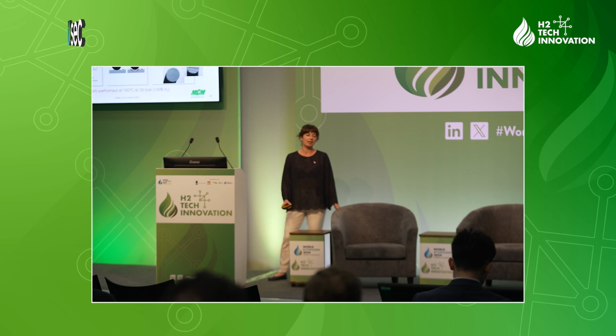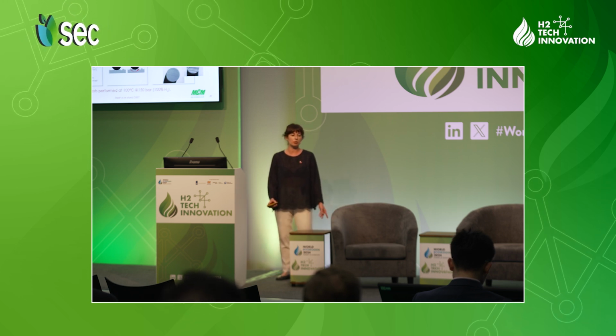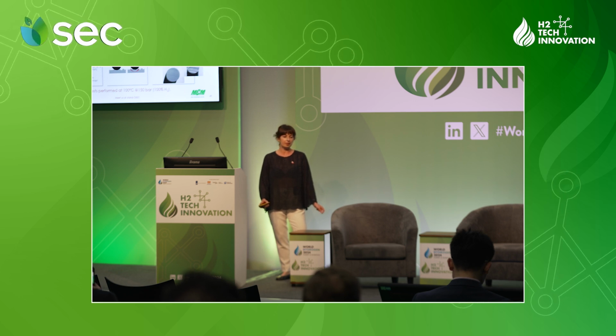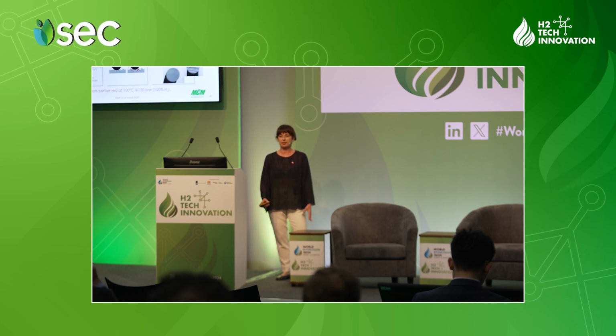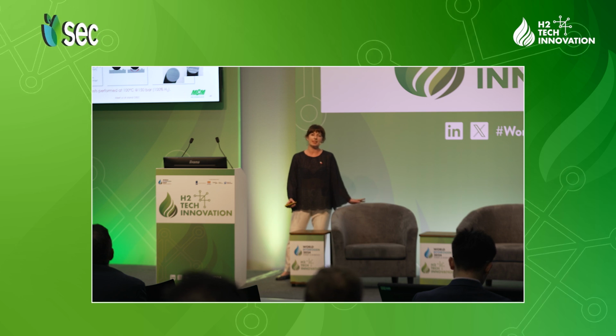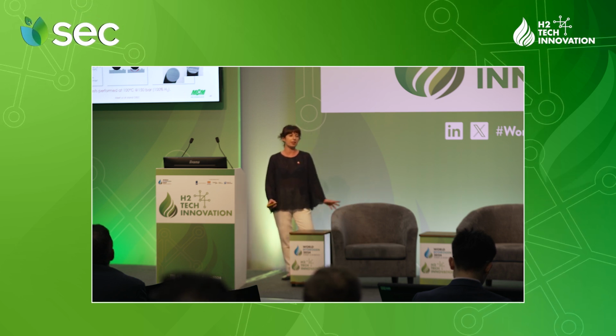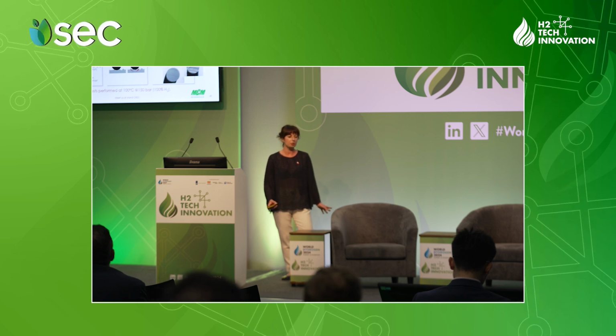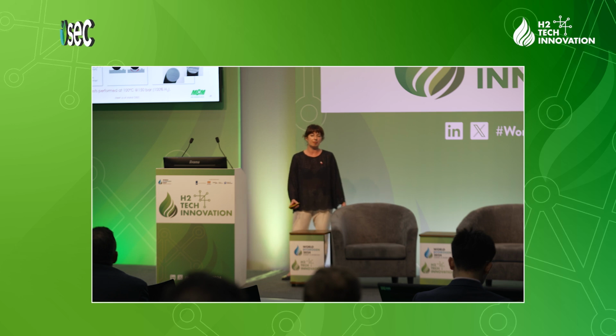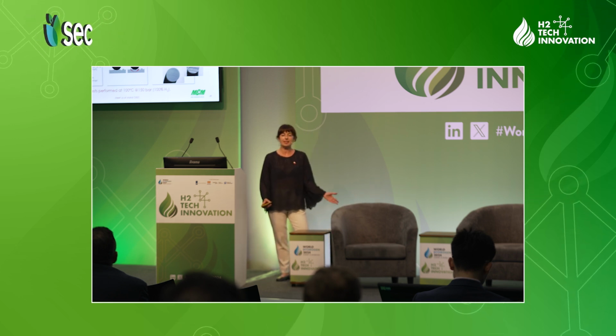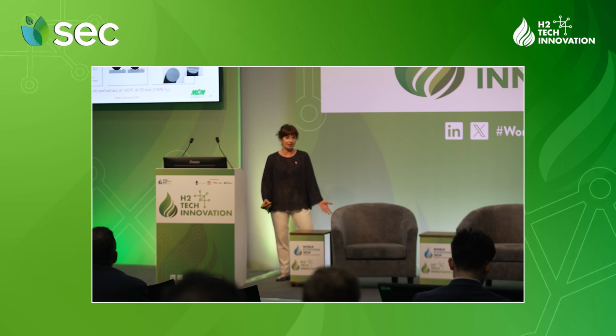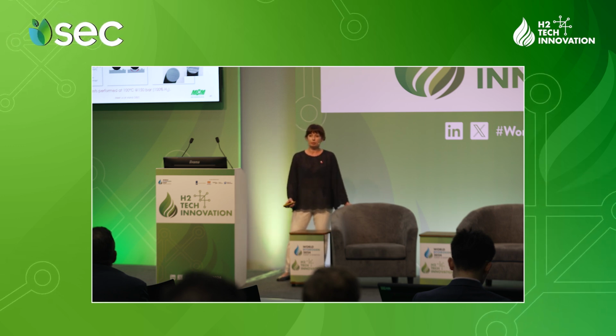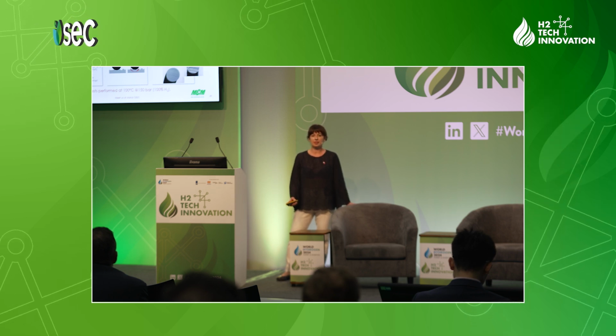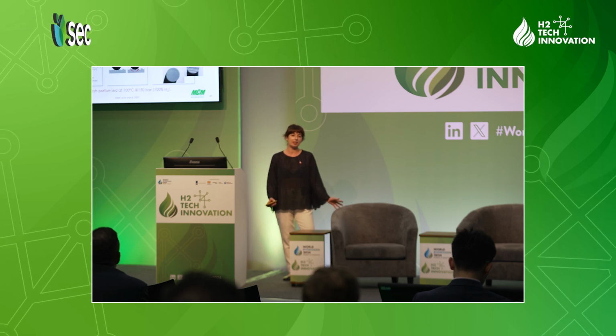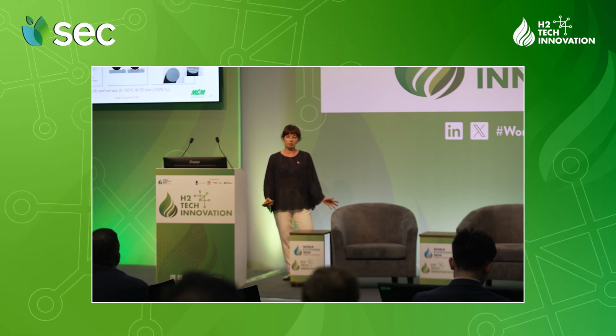So what we did on these high hardness compounds, so 90 Shore compounds, was to evaluate some key properties that we believe need to be considered when working with gases at high pressures. First of all, permeation to gases. Permeation, when you have a gas in contact with an elastomer, is a key parameter to be considered. Permeation is the product of solubility and diffusion, basically, and will depend on many factors. First of all, temperature and pressure, then thickness and surface area of the material exposed to the gas itself. Polymer type and compound formulation will play a role. And then gas type. Of course, different molecules will have different sizes and will also have different compatibility with the materials they are in contact with.